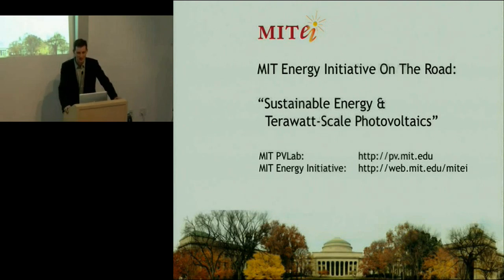Certainly. So the essence of tuning the band gap, so the band gap basically means the energy at which the semiconductor begins to absorb light. And anything with a higher energy than that, the semiconductor can absorb light and transform that into electrical current. So the band gap is a very important material parameter. You match that up with the solar spectrum and try to absorb as large of a solar spectrum as you can. And the material will absorb light most efficiently at the band gap energy. So you can stack different materials one on top of one another that absorb most efficiently at different regions of the solar spectrum, thus achieving a very high efficiency solar cell.